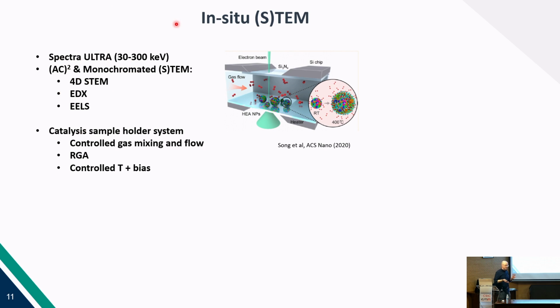But it has a different advantage. You could say, okay, this is similar to the other one. But no, this is really adapted for in situ experiments. Because in this one, you can change the voltage as much as you want. You can go from 30 to 300, and in 2 minutes, work again without any difference in the calibration. So it's keeping the intensity in all the lenses while you are changing the voltage. That means you can go from 30 to 300 in a moment and just continue working. With the other one, you need to wait for 1 day sometimes, waiting for the stability of the lenses.